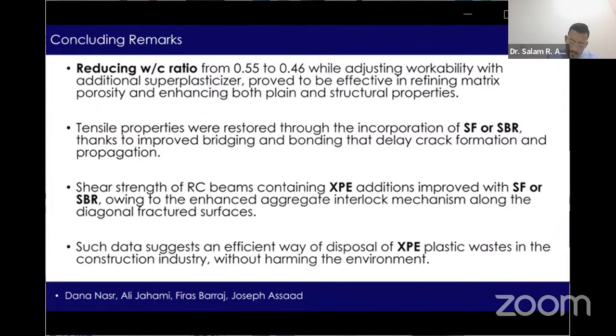One main alternative proposed in this work is the reduction of the water to cement ratio from 0.55 to 0.46 while adjusting the workability with additional superplasticizers. This alternative was found efficient to refine the matrix porosity and enhance the plain and structural properties of concrete containing XPE plastic wastes. Other two alternatives were also proposed in the study and were based on incorporating steel fibers and